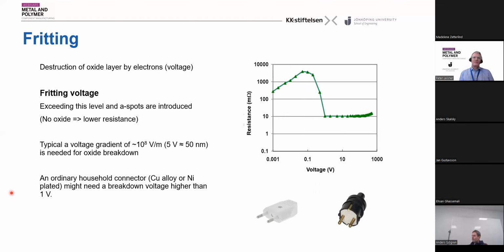So for materials which have an oxide film, if the oxide film is intact, there will be a high resistance. And therefore you will typically be able to grow a gradient over an oxide film of 10 to the power of 8 volts per meter. And if I translate that into something more relevant for the scale of contacts, that means 5 volts for 50 nanometers of oxide, which is needed for breaking down the oxide film.